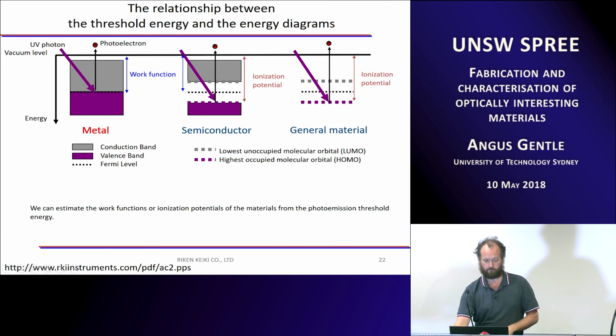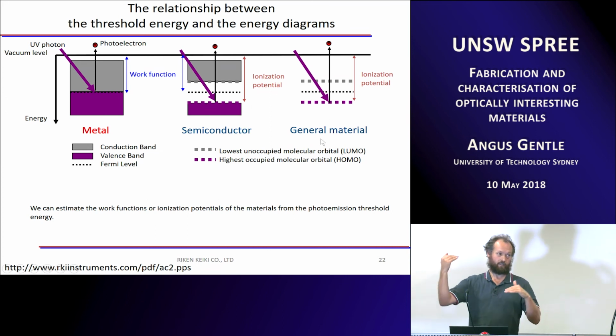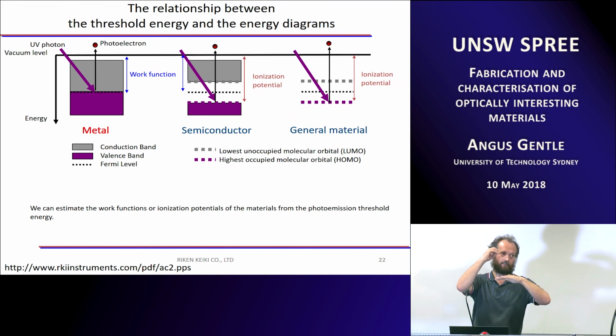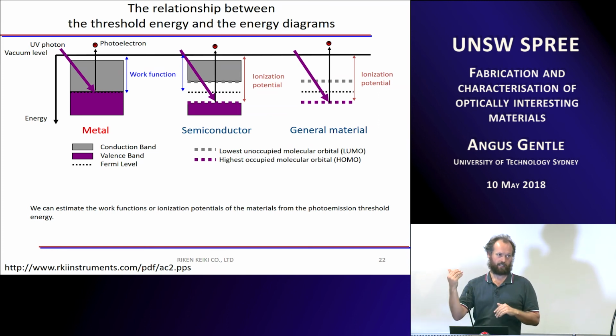So this is a slide from the guys who make the PESA instrument. Saw it online, described it nicely. So for metal, it's a work function. For a semiconductor with no defects in it, you're measuring the valence band. If you've got something else, it's really the highest occupied state. So if you've got defects in it, and you've got the valence band, some defects up here, that's what you're seeing. And that's usually what works as the thing that's contacting your devices.